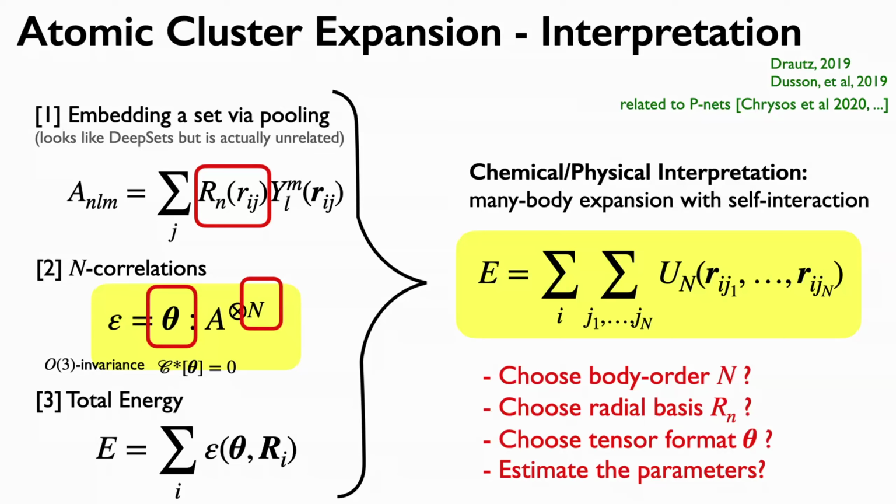So you mentioned that one advantage of having a rich representation is you don't need nonlinear models. Is that for speed? Is the slow bit the nonlinearity, or does the representation get so rich that it's actually slow to compute? Very good question. I meant to talk about it and forgot, so thank you for the cue. The way I've written it, it is a linear model, but I can pick whatever tensor format I want. And if I choose, for example, a Tucker format for this parameter tensor theta, I get a highly nonlinear model. So our code can in principle support such formats.